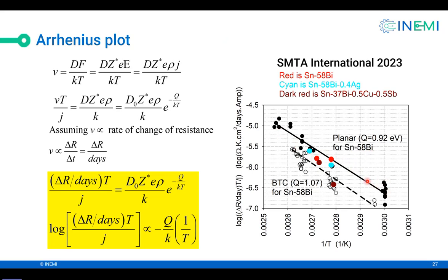In this study, which we published at SMTA International 2 years ago, we compared the bottom terminated component test results with the planar solder. They're very similar, though there's an offset. So here we're comparing two different techniques of measuring electromigration in tin bismuth alloys. For this paper, we got the best paper award at this conference. But these are old results, so let me show you the new ones.